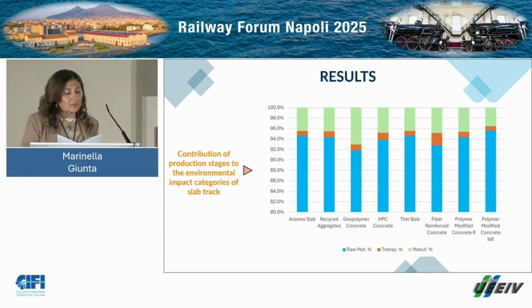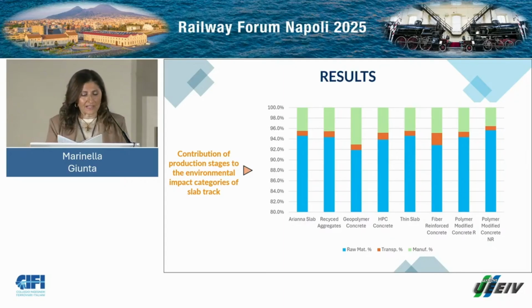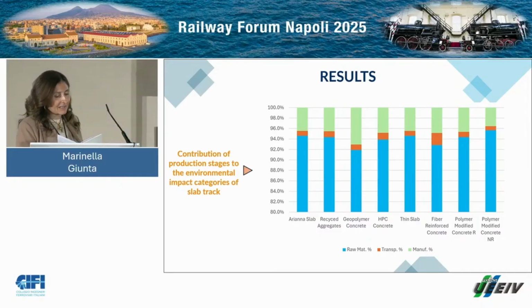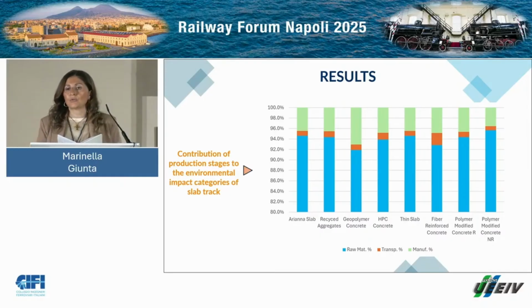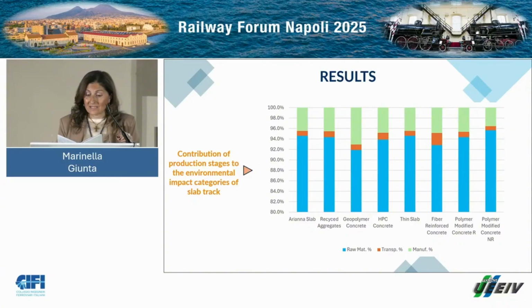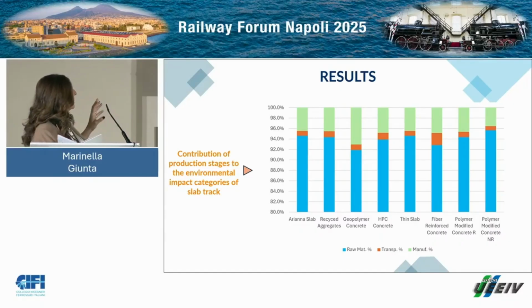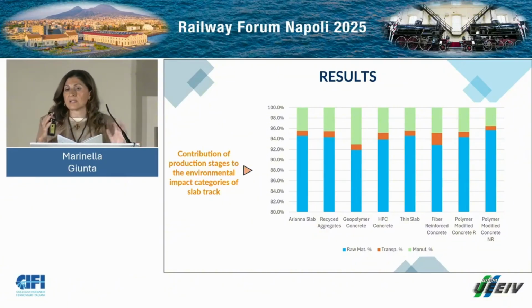Regarding the contribution of the 3 production stages we considered to the environmental impact categories of slab track, it's possible to observe that raw material contributes 90% and more to the values of the impact categories. This highlights the need to focus attention on the selection of the material, on the design of the materials. This aspect can contribute to improve the sustainability of the track. The manufacturing contributes about 3 to 6%, while the transportation has a minor contribution, from 1 to 2%.